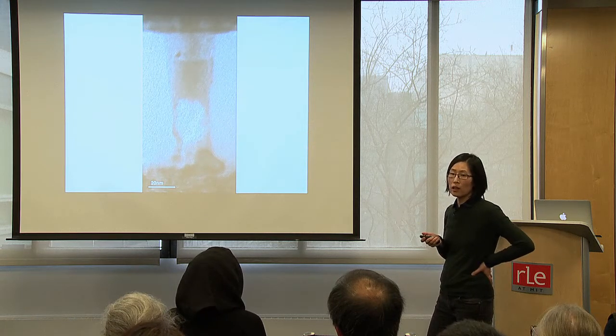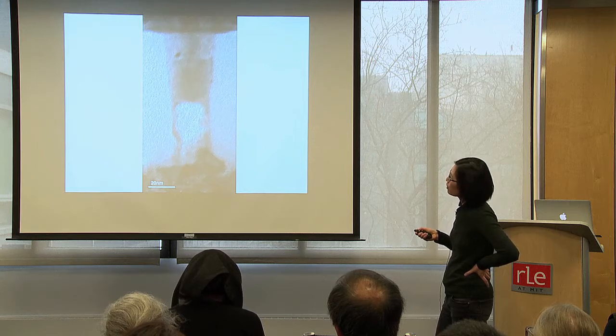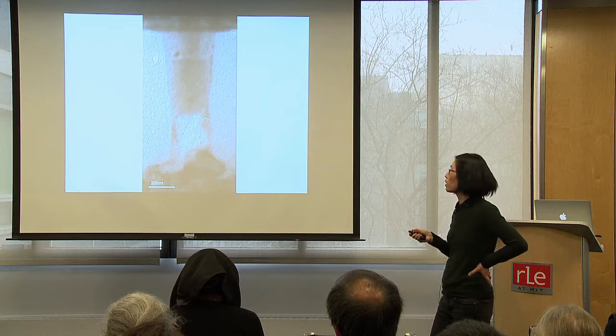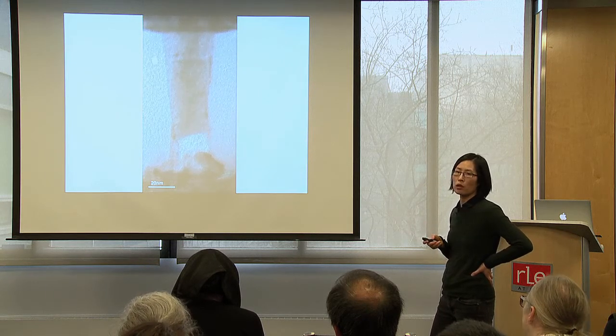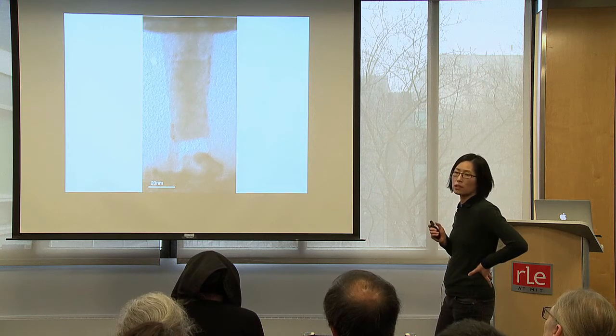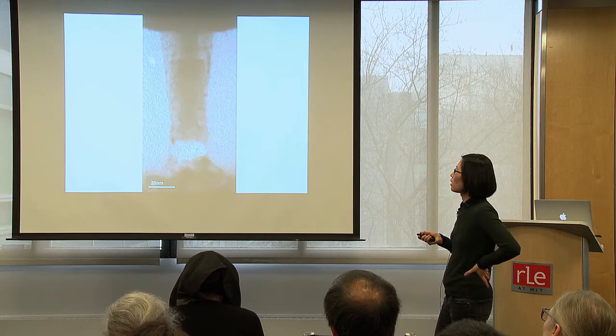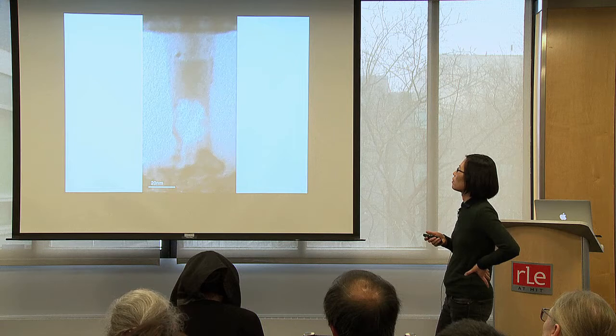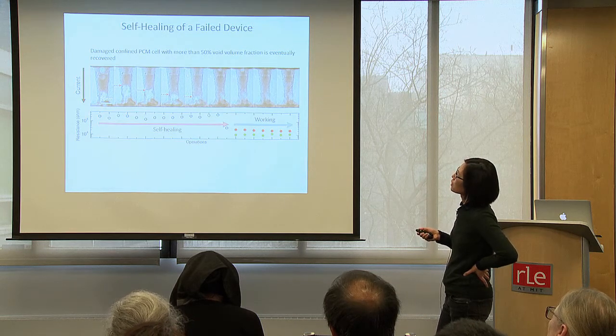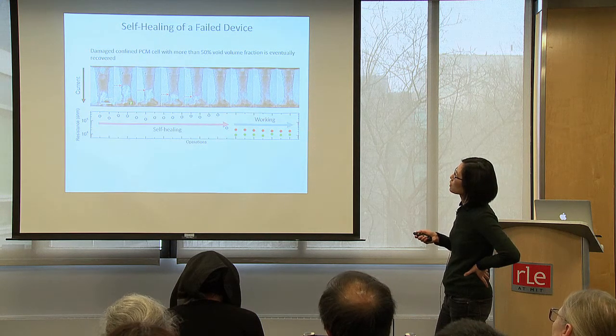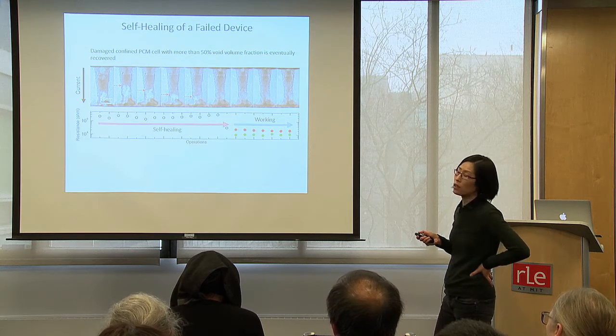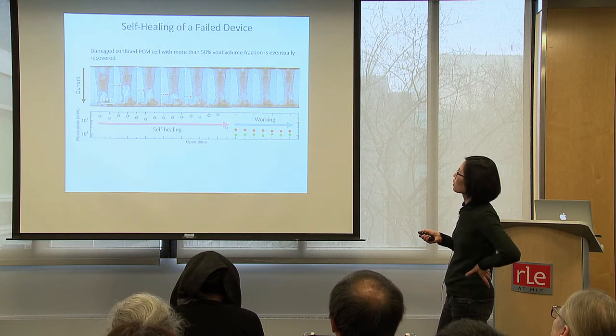And the fact that this IBM device has a metal surfactant layer means that an initially failed device, where more than half of the device was a void, you can gradually fill it back because you have a very resistive element where the current can still flow. So you can heal the device. Now it failed. Here, the resistance was initially high. You're measuring resistance through the metallic surfactant layer. Once it's filled, then you can do some switching.